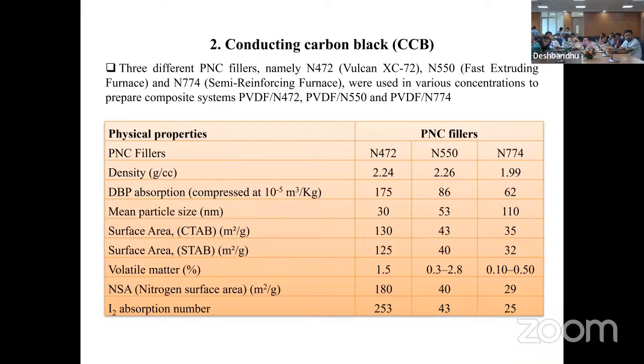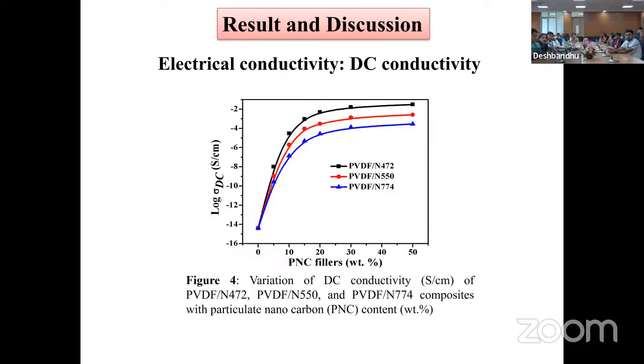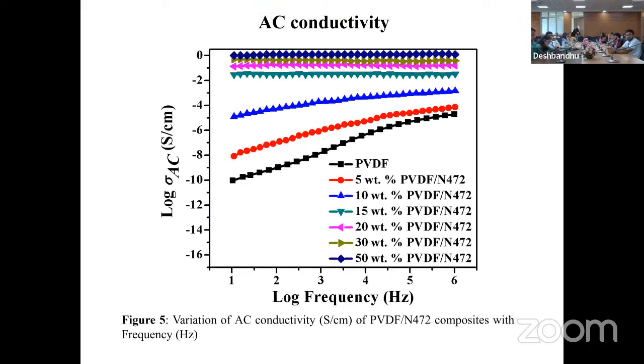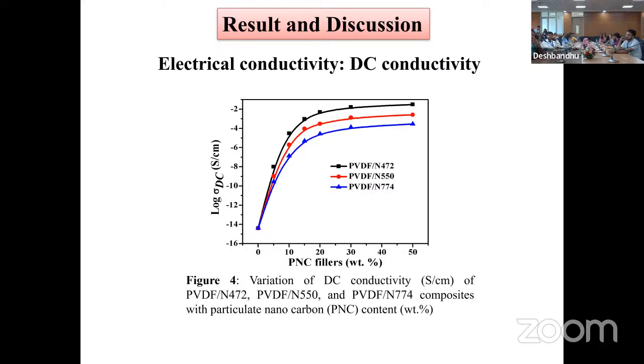For conducting filler, I have used 3 fillers: N472, N550 and N774. These numbers depend on the size and structure of these particles. Here, electrical conductivity, you can see easily that the PVDF N472 material is showing higher conductivity in comparison to N550 or even N774. Similarly, here I plotted the AC conductivity. It is also showing the same trends. And here I have taken 5 weight%, 10 weight%, and 15 up to 50 weight% of N472. Why I have taken N472? Because it is showing better results in comparison to the N550 or N774 carbon blacks.